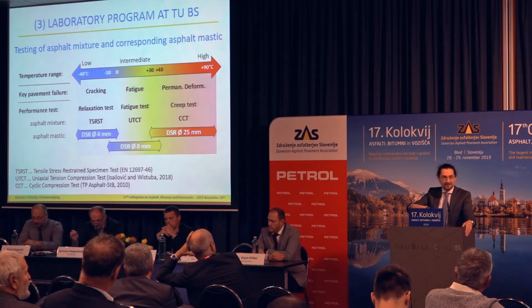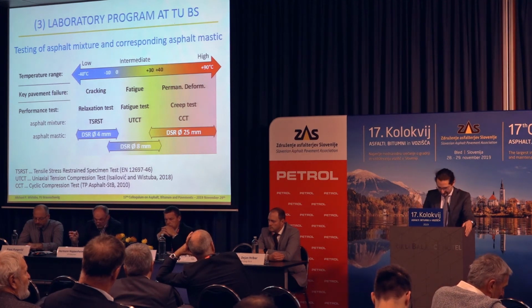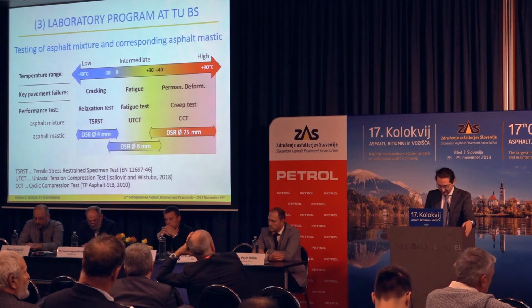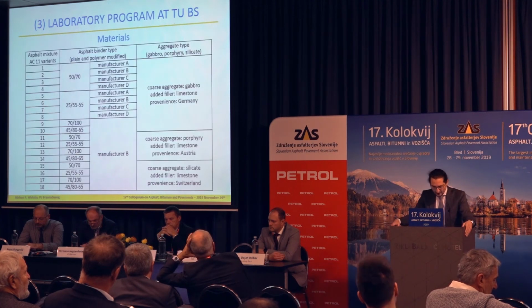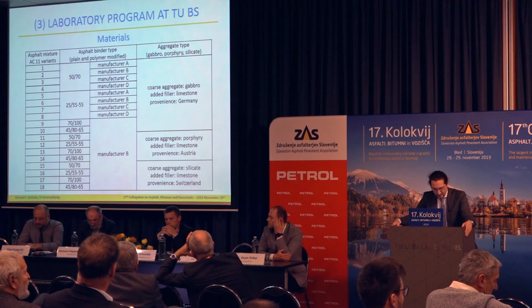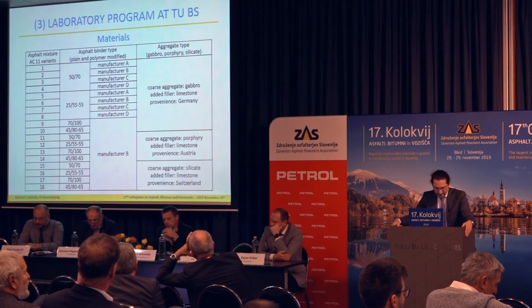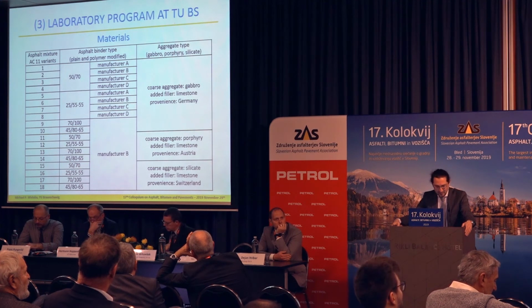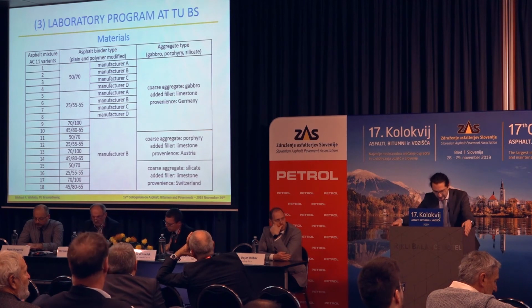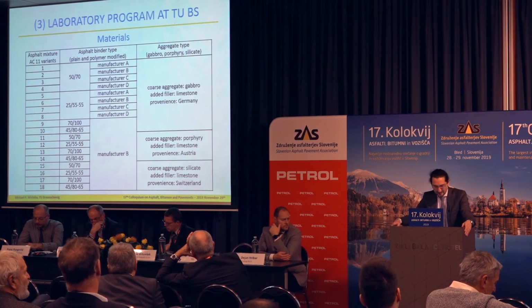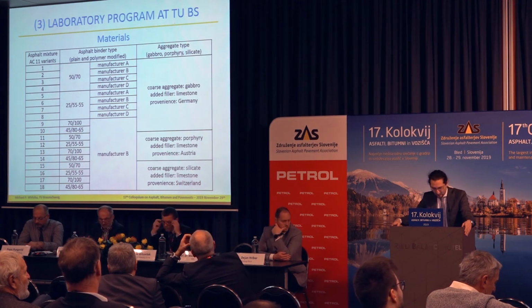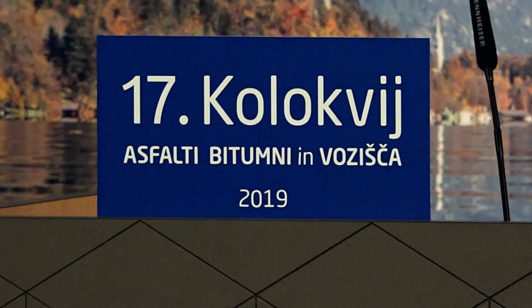And then we compared the results with more or less the same idea of material testing, but at the asphalt mastic scale, tested with the DSR. So in our study, sponsored within the program Vegas, within the German-speaking countries, we selected these materials. So we put together 18 different asphalt mixtures. We selected 2 different plain binders, 2 different polymer modified binders, 4 different manufacturers, and 3 different aggregate types for the coarse aggregate, and we added limestone as a filler.